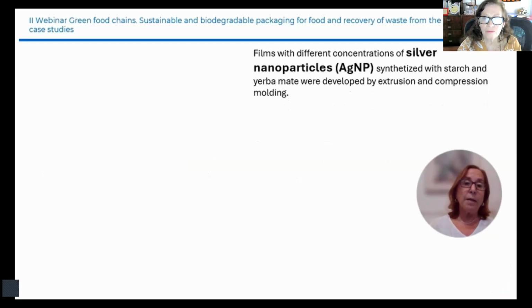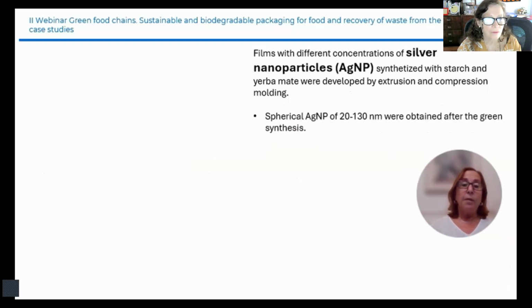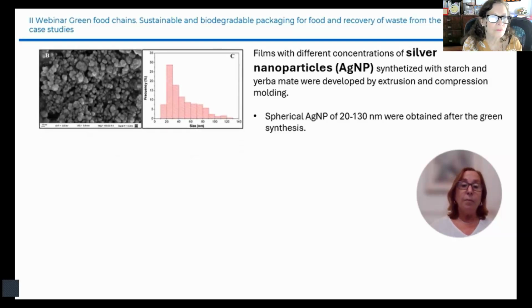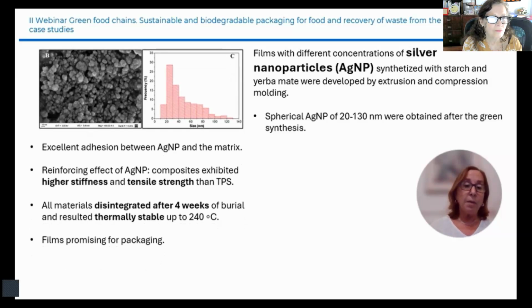After the previous results, we also tried the use of silver nanoparticles, which were synthesized with starch and yerba mate, and the films were obtained now with a more scalable processing technique such as extrusion and subsequent compression molding. The spherical nanoparticles were obtained after the green synthesis, as you can see in the scanning electron microscopy micrograph, and the nanoparticles had excellent adhesion with the matrix.